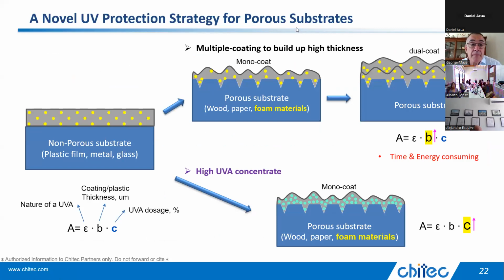In this particular slide, what we're trying to show is that if you want to load up a coating over a porous substrate, or a non-porous substrate, where you want to get a certain UV absorptivity to protect the material below, if you go back to Beer's law, you have to get that certain total concentration of material. Well, if you go at 2% or maybe even 3% of just a standard UV absorber, which is getting fairly concentrated in the coating, in order to get it thick enough to absorb all the light, you might have to put on 2 or even 3 layers of coating.